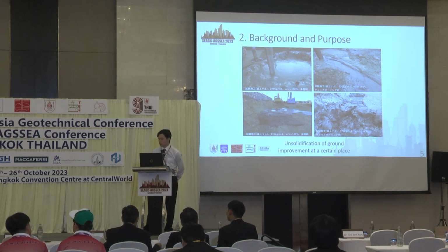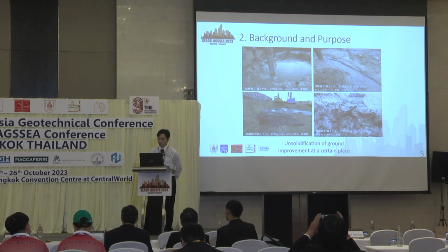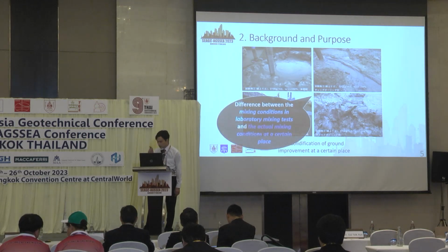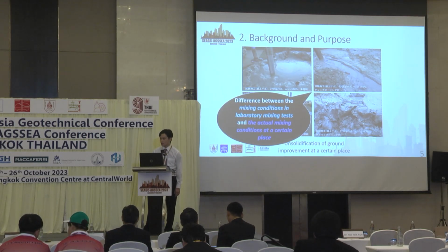And background and purpose will be given next. As you can see from these figures, unsolidification of ground improvement occurs at a certain place. You can see that the cement has not solidified in the ground and is overflowing to the surface. The cause is thought to be the difference between the mixing conditions in the laboratory mixing test and the actual mixing conditions in the actual equipment at a certain place.